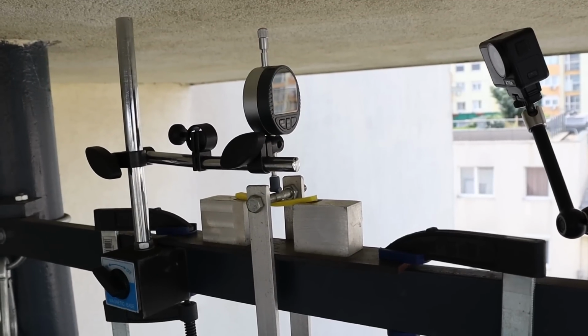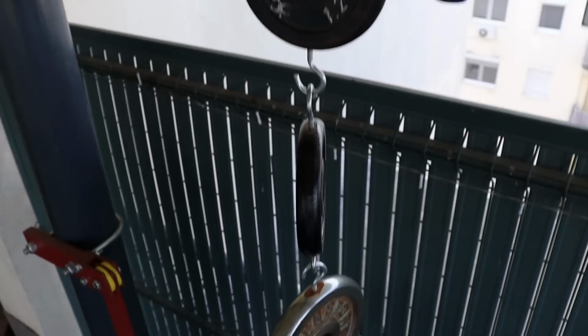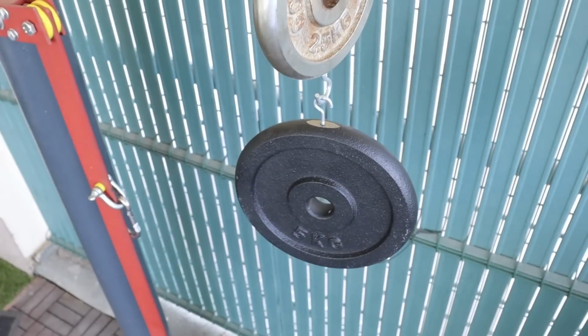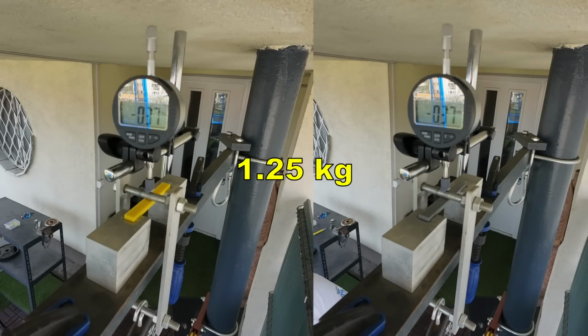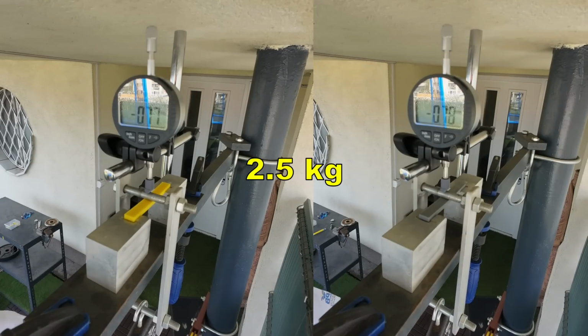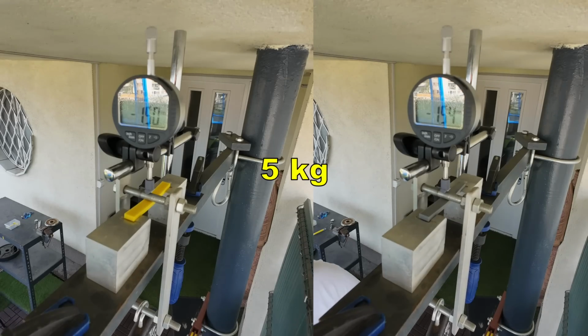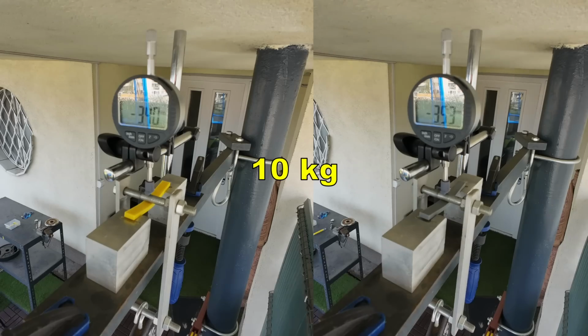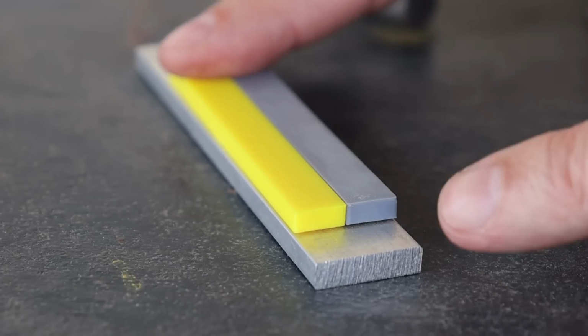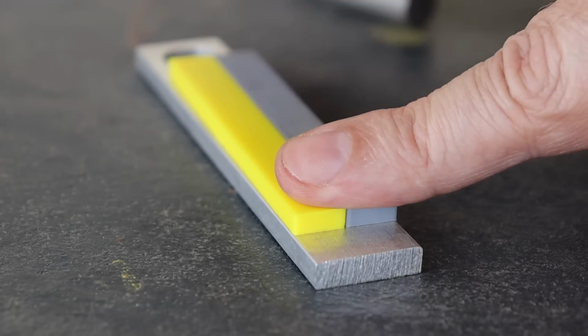3-point bending test, and here you can see all loads placed, but they will be placed one by one, and I'm measuring the deformation after 30 and 60 seconds under one load. And this is a timelapse speed up video. At the beginning very similar deformations, but later the ASA had a little bit bigger deformation. I will show you everything in the results part. And I can see some minimal permanent deformation on both test objects.